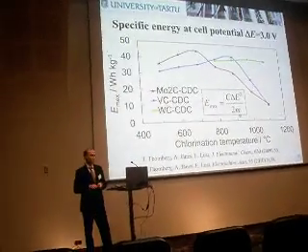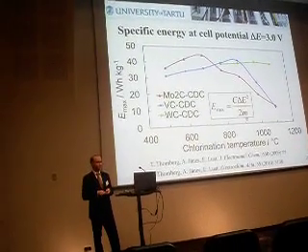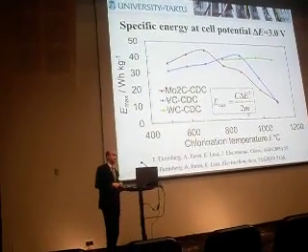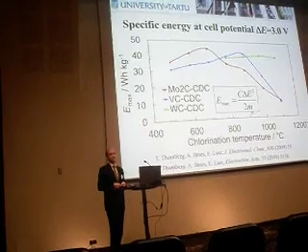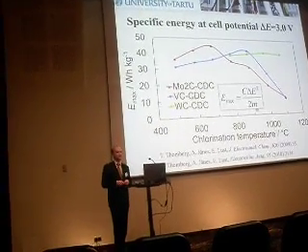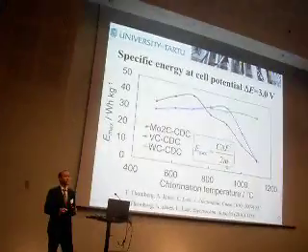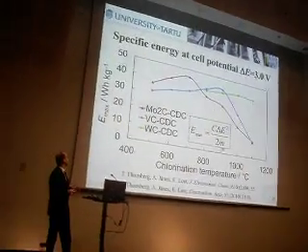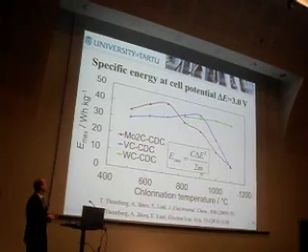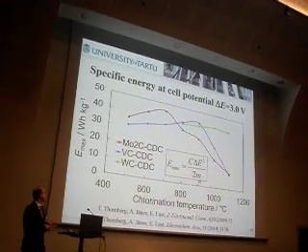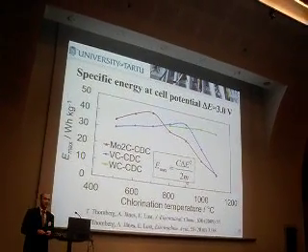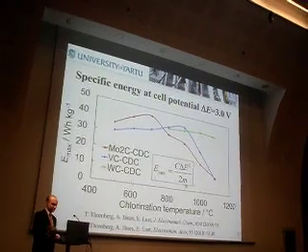And when we calculate it into the specific energy and compare it with other carbide-derived carbons, then we see that the material is quite average. We can store about 41 watt-hours per kilogram.